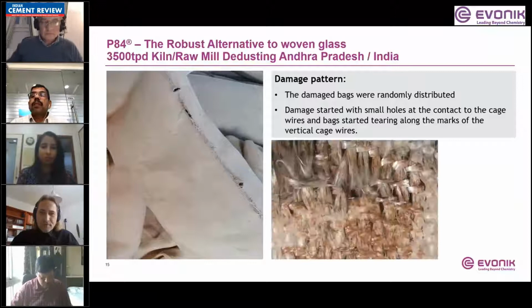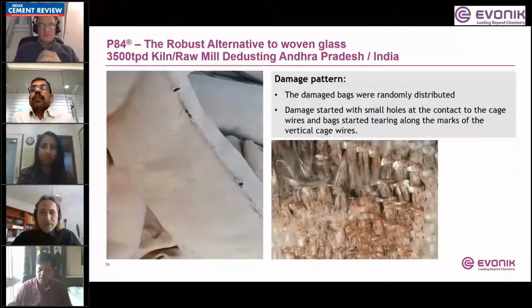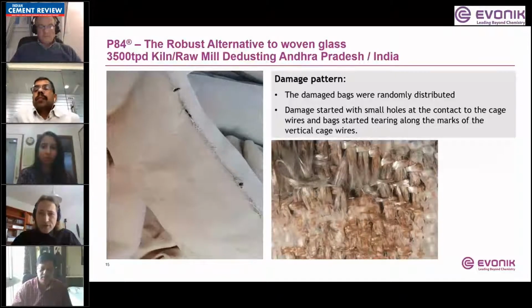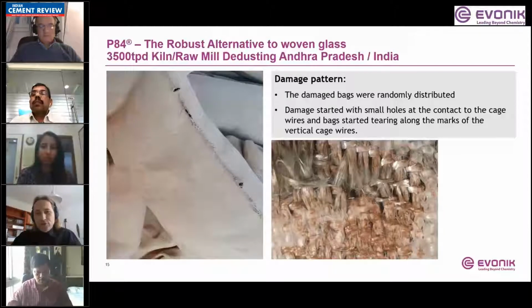You see small holes, and this shows the cleaned starting hole. And you see that many of the glass fibers are already broken. It's difficult to judge whether the membrane is broken first or whether the glass fabric started breaking and then the membrane was tearing. It doesn't make a difference. The outcome is the same. You will observe increased emissions.